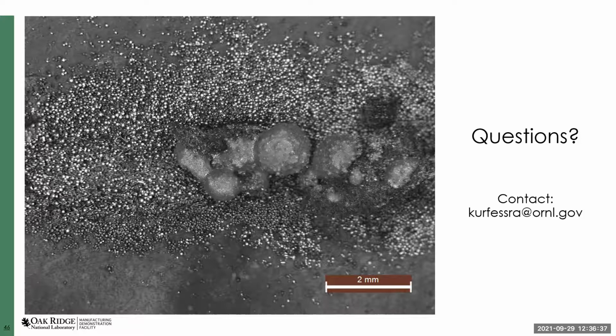The other important thing is more qualitative observations. I want to make sure I avoid anything catching on fire. Any kind of safety concerns like that would make this really unusable in industry, so it really wouldn't be applicable in many larger scale spaces. Also, I'm looking at how much metal is deposited. For example, with the glass fiber filled nylon and PLA, we see a much more significant amount of metal being deposited and remaining on the surface, versus the PLA and the carbon fiber ABS, which looked more like a spray of material versus a bead or a ball of feedstock that has been melted and resolidified.